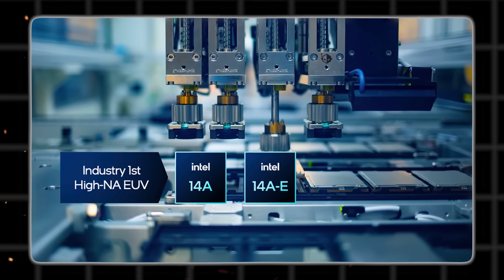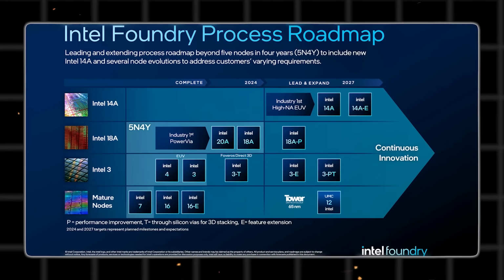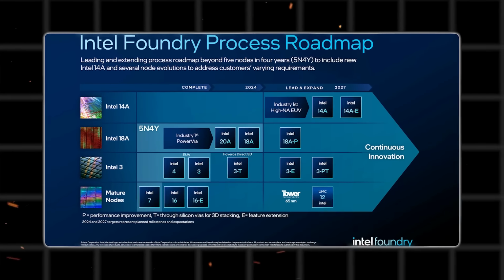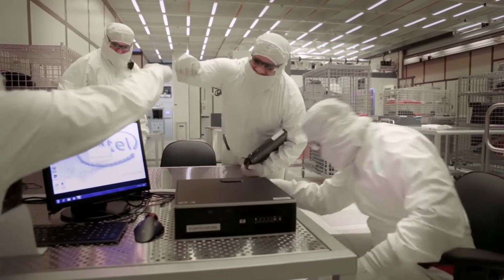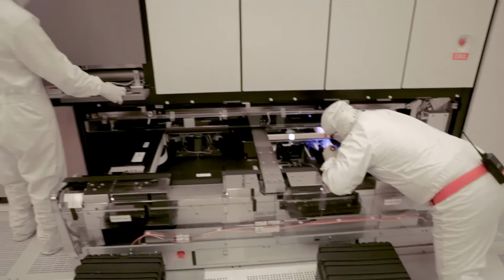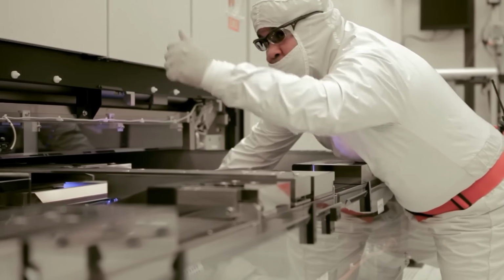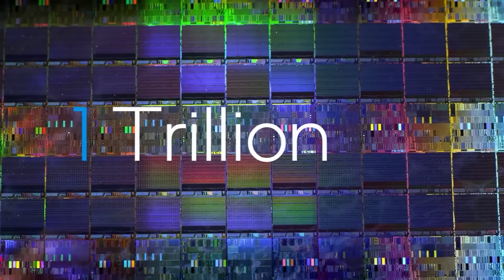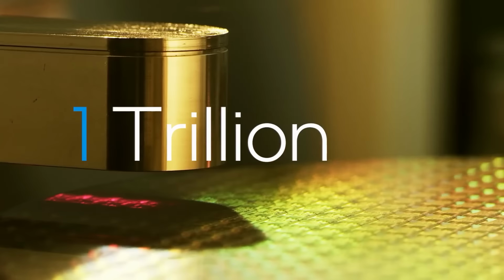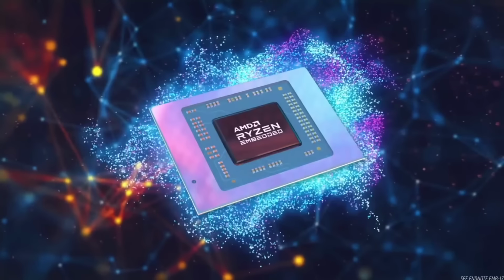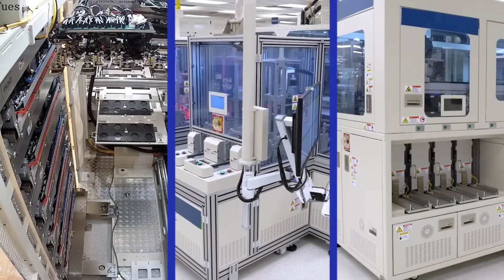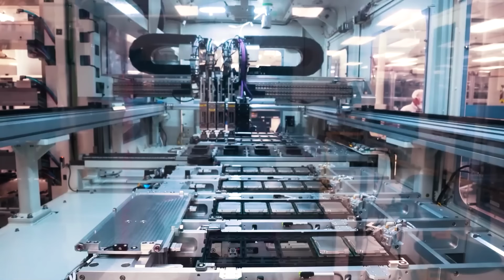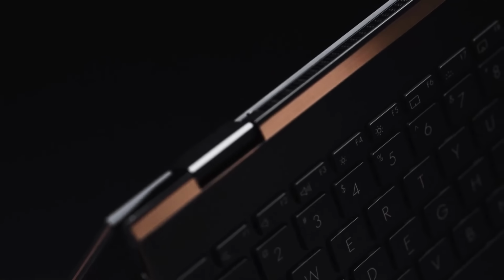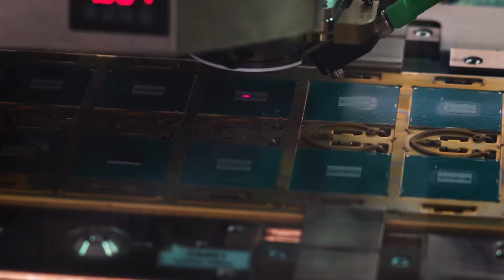Now, Intel's 14A node, which sits within the 1.4 nanometer class, is where it all comes together. Intel is combining High-NA EUV with DSA for at least 3 critical layers on the 14A process. This is not just an incremental tweak, it's a fundamentally different manufacturing approach. Intel has essentially gone all in on High-NA EUV in a way that neither TSMC nor Samsung has. Both have ordered High-NA tools, but only for R&D. Intel is the one pushing for high-volume manufacturing with these machines, ordering multiple ASML High-NA EUV tools and committing hundreds of millions before the technology was fully proven.